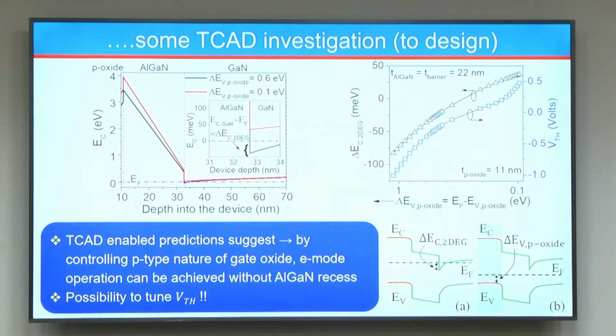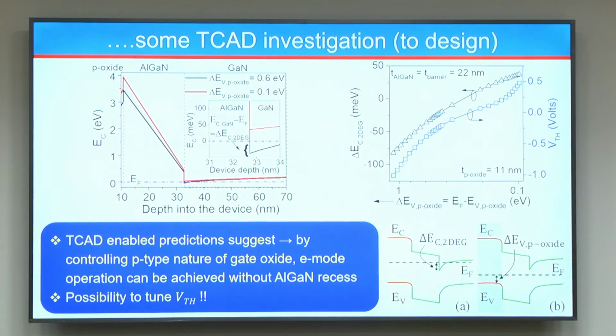So we did some computations to figure out whether, like pGaN, it would work in this case, and we studied at that time the thickness as a variable, and at what point the charge is sitting, or in the energy space at what point the charge is sitting, which means how far or how close the Fermi level is from the valence band in case of the oxide. And as you bring this closer and closer to the valence band, you see that even in the GaN region the Fermi level shifts away from the conduction band, which basically is equivalent to depleting the GaN layer of the 2DEG, right. And we also investigated thickness, what kind of thickness you need, and what kind of energy separation you need.